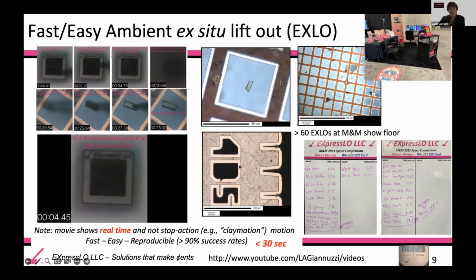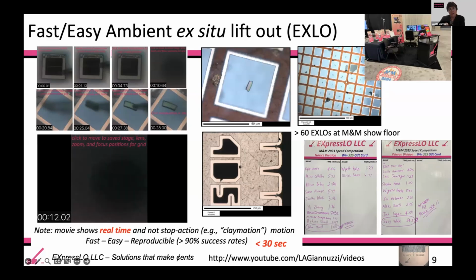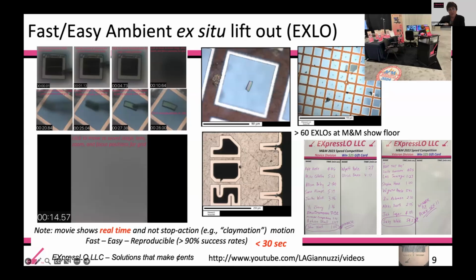These specimens can be manipulated to either a wholly carbon grid or a carbon-coated grid. We have these patented grids. These are half grids, with shapes that allow the specimen to rest on the grid itself without any carbon support across it. This allows you to post FIB mill the specimen. If the specimen's too thick, you can put it back in the FIB. You can put it in, for example, an argon ion mill, etc.